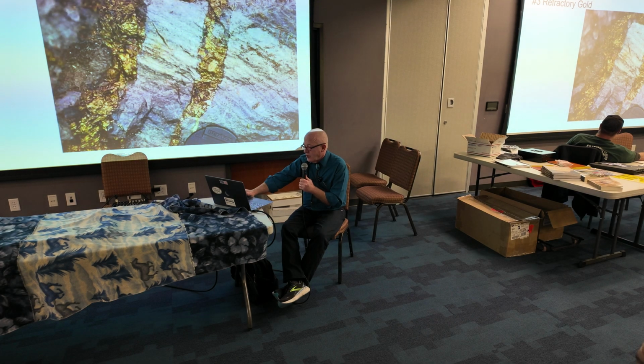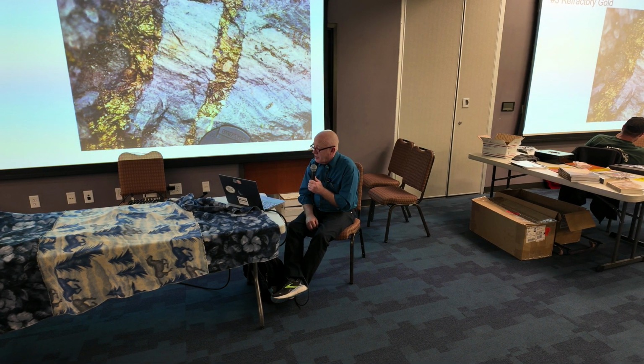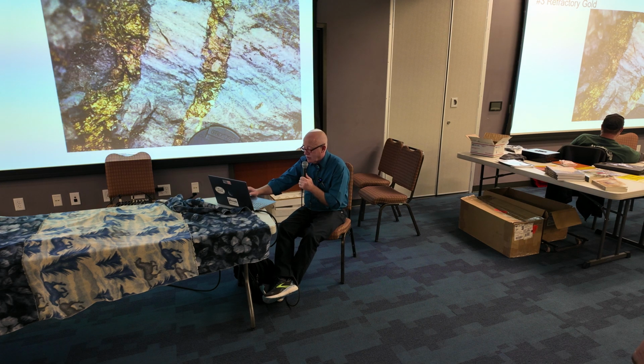All right, refractory gold. I told you this was going to be boring. Refractory gold is a type of gold where the gold is difficult to extract using conventional methods. It's often associated with sulfide minerals such as pyrite, arsenopyrite, stibnite, chalcopyrite, which encapsulates the gold particles and prevents them from being liberated conventionally by crushing and grinding. They have to be done through chemical methods, usually like a cyanide leach. So they grind it into a powder and then use a cyanide leach.